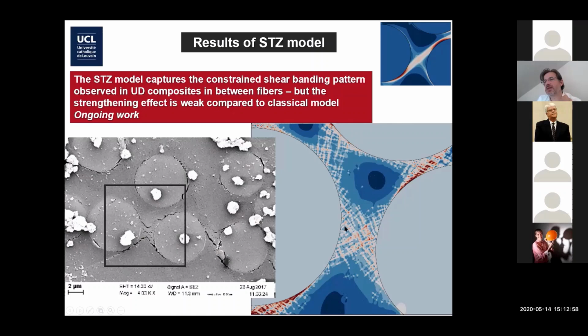And I think up to now, what most people do is put a cohesive zone model to simulate the decohesion process. By fitting the right peak stress and energy in the cohesive zone, somehow they take into account the complexity of this interface layer, and they just merge everything in a black box. And it's better to do that than nothing, of course. But there is probably a lot of interesting physics to scrutinize at those length scales, and I understand that's what you do, and that's very interesting.